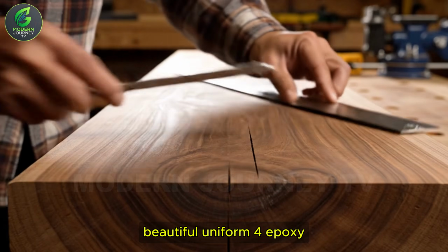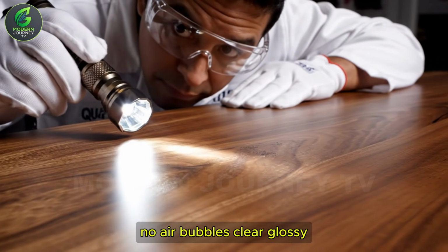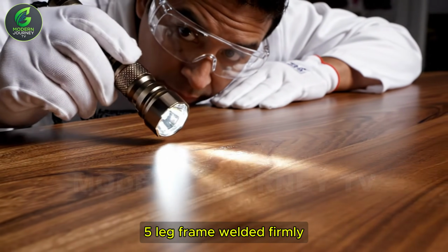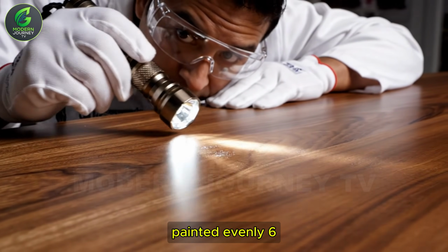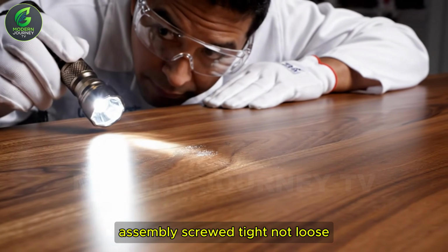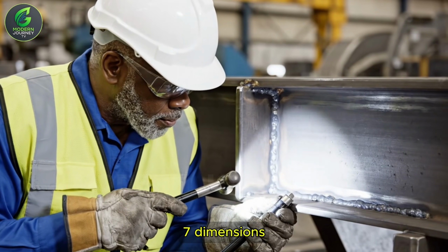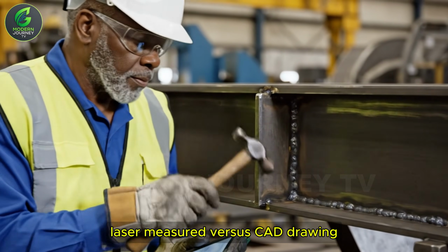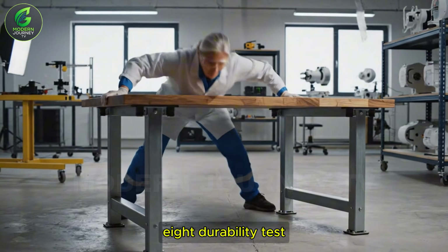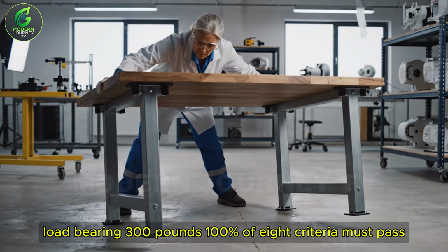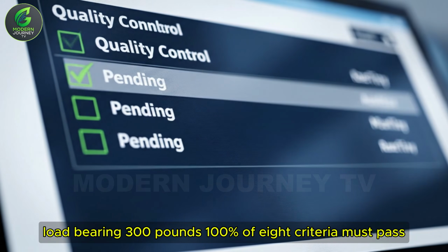4. Epoxy, no air bubbles, clear glossy. 5. Leg frame welded firmly, painted evenly. 6. Assembly screwed tight, not loose. 7. Dimensions laser measured versus CAD drawing. 8. Durability test, load bearing 300 pounds. 100% of 8 criteria must pass. Pass rate, 92 to 95%.